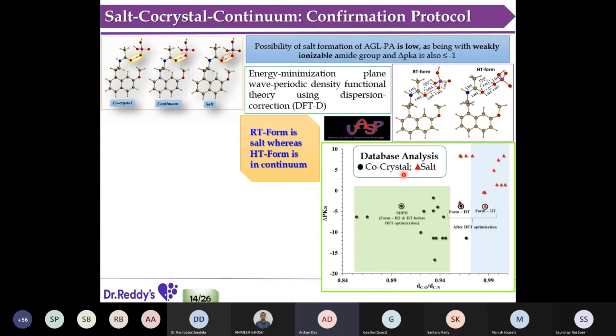Now you see that we have color coded. All the black dots are the co-crystals already defined by single crystal in the literature, in the paper and in the database, and all the red circles and red triangles are the salts. Surprisingly, with the powder data, both structures were sitting at the same place, because atomic positions and bond lengths were not correct. But when we corrected the structures with the DFT-D calculation, then we can see the difference.